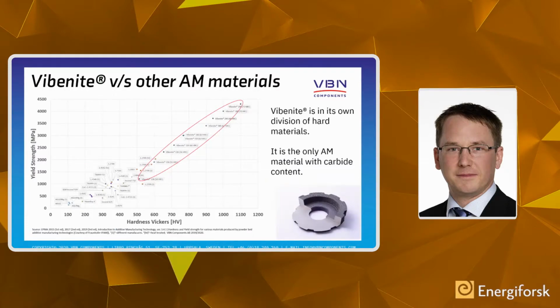If we compare Vibenite with other additive manufacturing materials, then we do like this. We use the graph from the European Powder Metallurgy Association, and then we put in the existing AM alloys and look at the hardness and the yield strength. Then you can see that here you have the typical steels and titanium and cobalt chromium alloys that exist today. Here in this region, you have a number of maraging steels, which are also very good for the applications. And here we have the Vibenite alloys. So we are in a totally different scale of hardness and wear resistance. In addition, these alloys also include a content of carbides, which is also very interesting, of course. So the hardness is one thing in wear resistance, but the carbide content is an add-on to that.